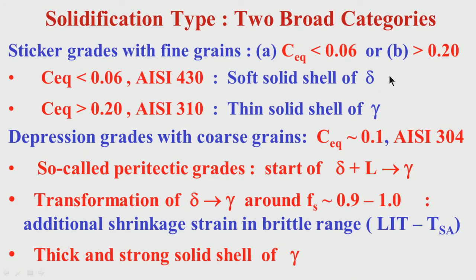Since we have delta ferrite solidification, and even after solidification we have delta for a certain temperature, we know that delta has relatively less high temperature strength compared to austenite, so it is soft. Now, when carbon equivalent is more than 0.2, or AISI 310, one popular stainless steel grade, we have a thin solid shell of gamma. Gamma is austenite, but the shell is very thin because of high incidence of micro segregation in austenitic solidification. So, either for very low carbon or low nickel equivalent, chromium equivalent, we have a soft shell, or for high carbon equivalent or 310, we have a thin shell. In either case, there will be sticking tendency and fine grains.